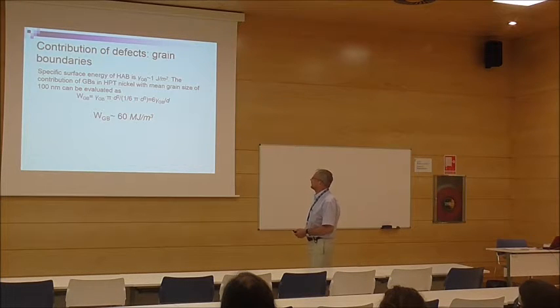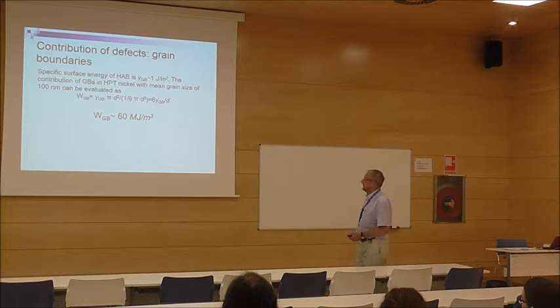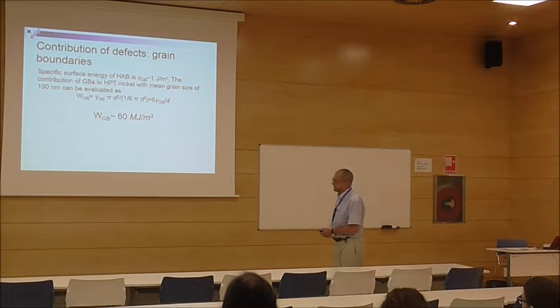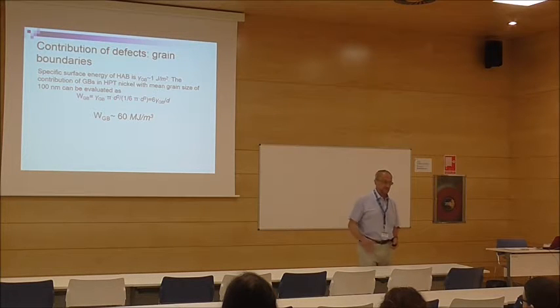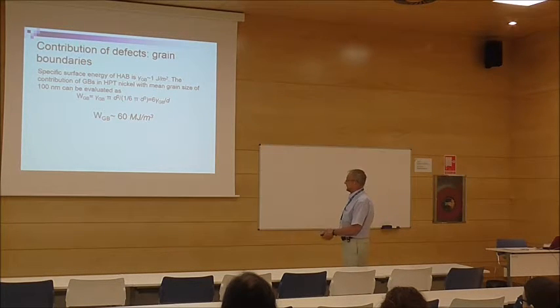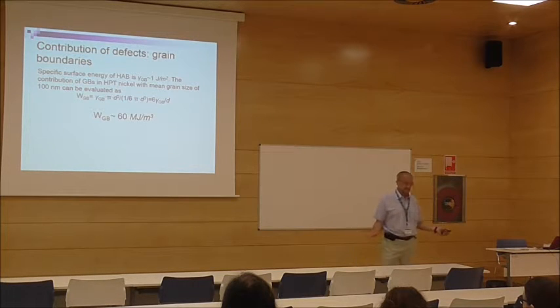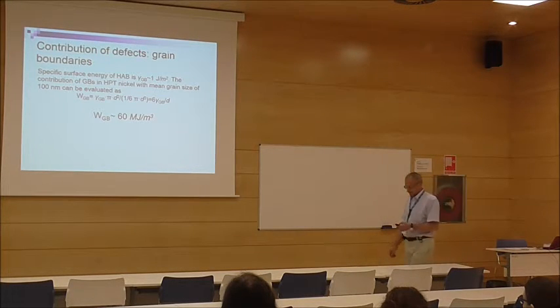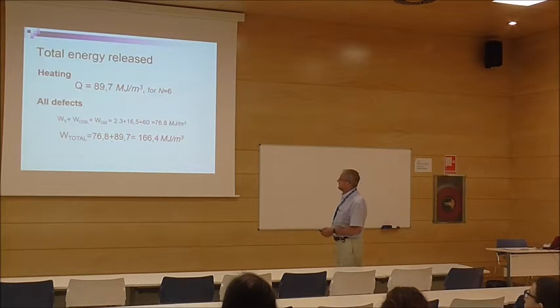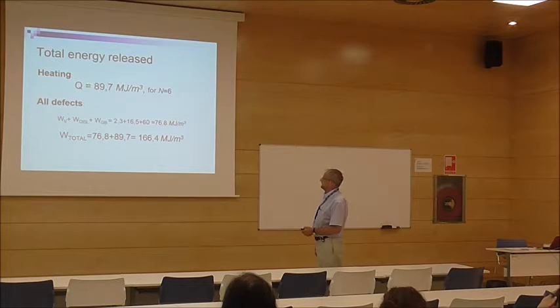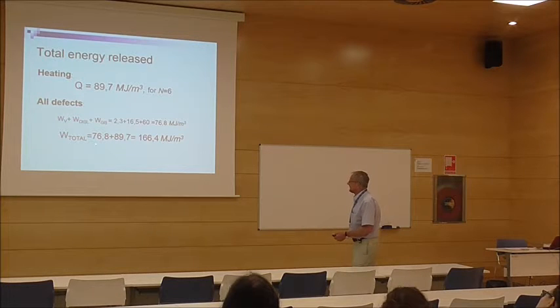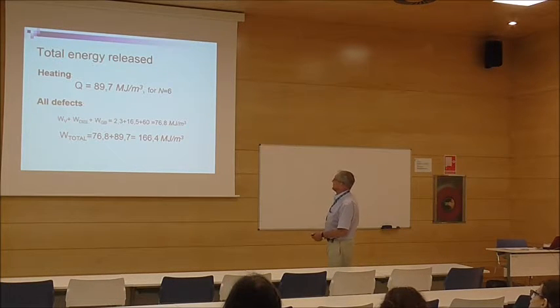And for the grain boundaries, it can be evaluated by the specific surface energy of high-angle boundaries, which is about 1 joule per square meter. And we calculate the total surface area per cubic meter like this. It gives the highest value, which is normal. And if we calculate everything, heating gives 90, and all defects give like 76. All together gives you 160 megajoule per cubic meter.